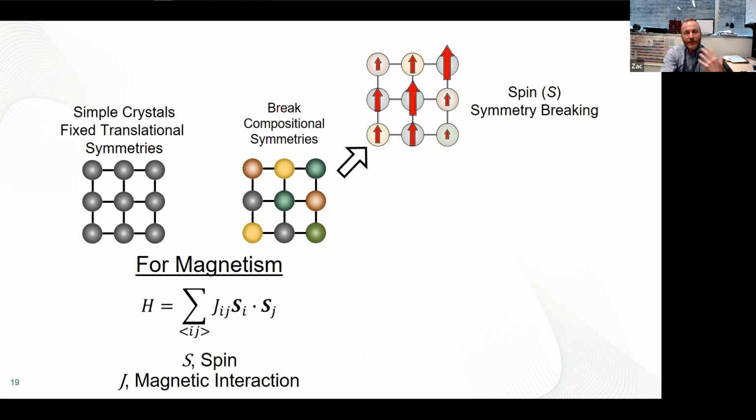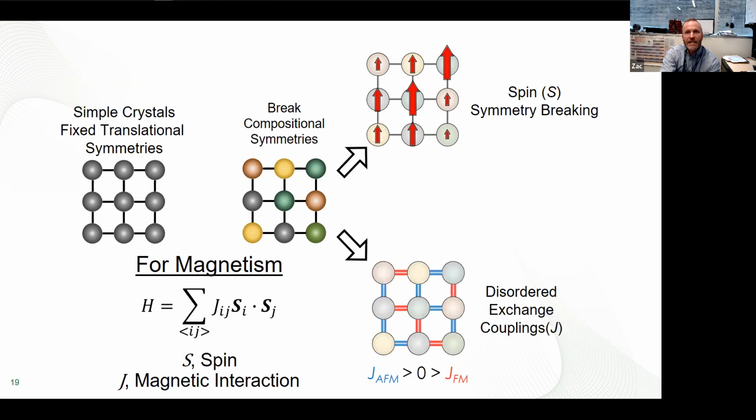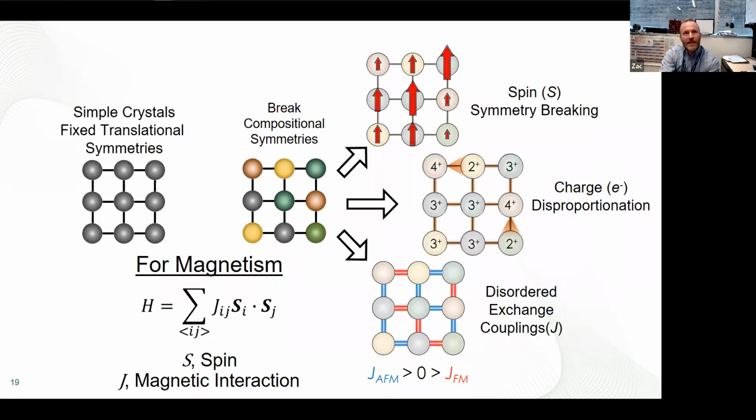Each of these different sites is going to depend on charge state and composition for what the spin contribution is. And of course, depending on the nearest neighbor environment, that's going to drive whether you have a preference towards ferromagnetic or antiferromagnetic coupling. This is, again, charge disproportionation and how charge sharing can happen. This is really, in my mind, one of the most exciting things going forward. For example, in a perovskite you would think you have a 3+ on the A site, a 3+ on the B site, and then -6 on your oxygen O3, right? You want to balance that out.